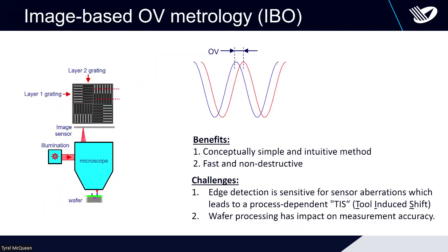Now, finally, for overlay: how to control the alignment of two layers on top of each other. There are two approaches. The first is image-based overlay. You put two gratings or multiple gratings into a marker, one in the top layer and one in the bottom layer. You take an image of that, and you try to get an image with a lot of photons so that you can determine the maxima of these lines with high accuracy. From that, you can determine an overlay shift. So it's image-based. You cannot resolve very fine structures, but you can determine the maximum of a point spread function very accurately.